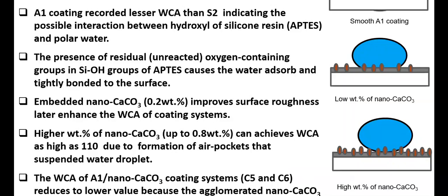On your right, you can see a smooth A1 coating system. The A1 coating system recorded a lower water contact angle than S2, indicating a possible interaction between the hydroxyl groups in the silicone resin and the polar water. The presence of residual oxygen-containing SiOH groups causes the water to absorb and tightly bond to the surface. When it is embedded with nano calcium carbonate, it forms a cushion which repels the water droplets, so it increases the contact angle between the coating and the water droplet.